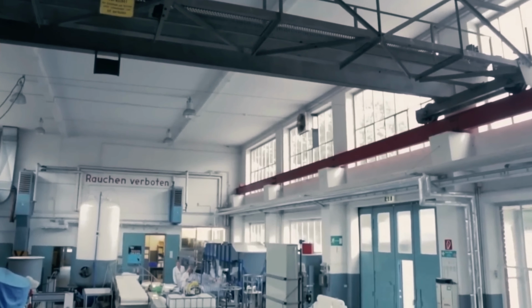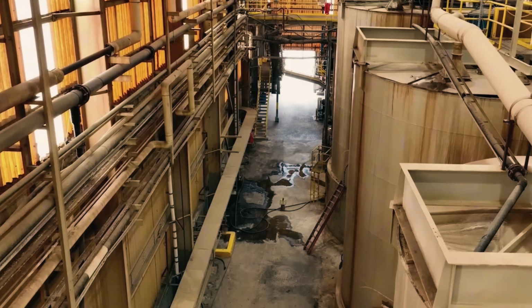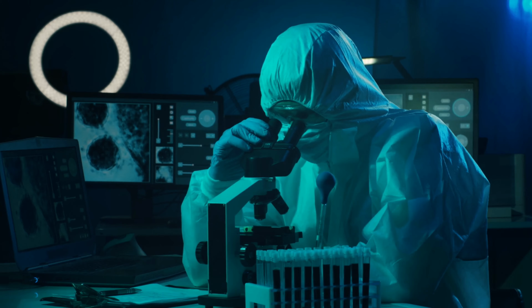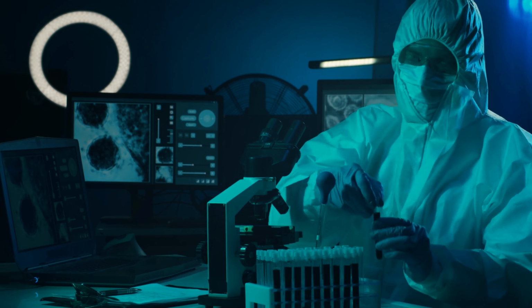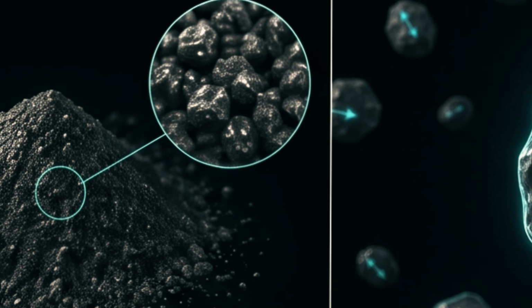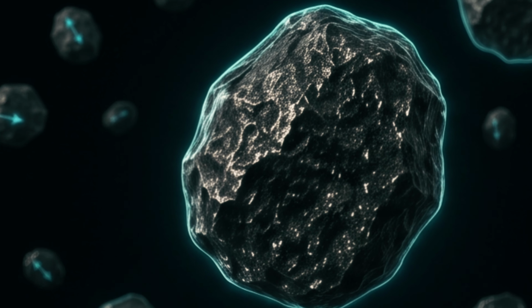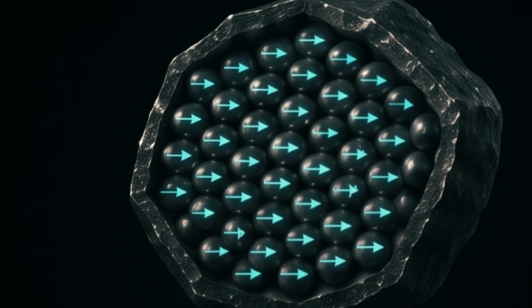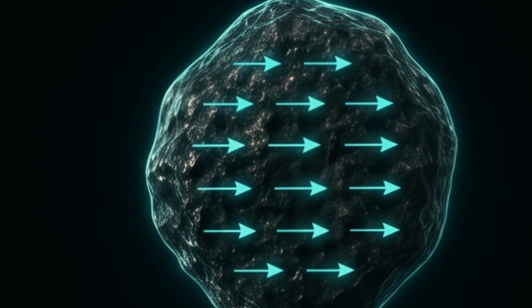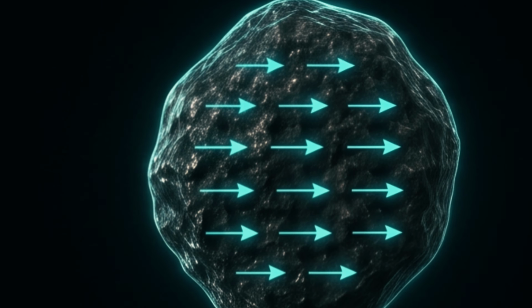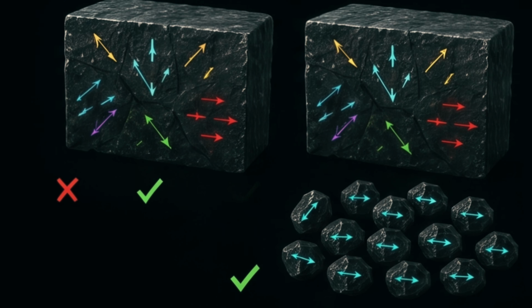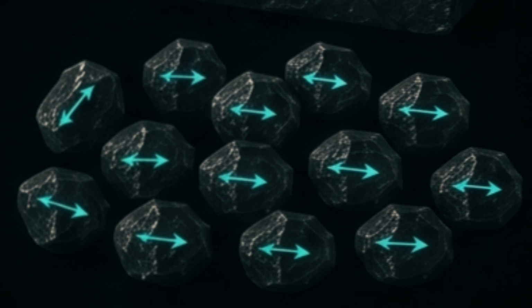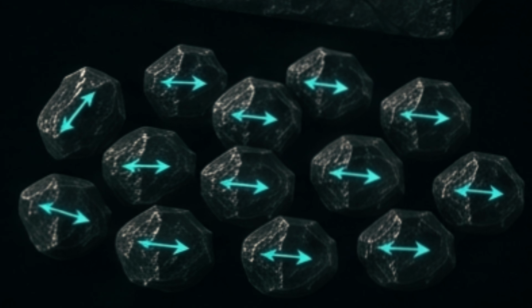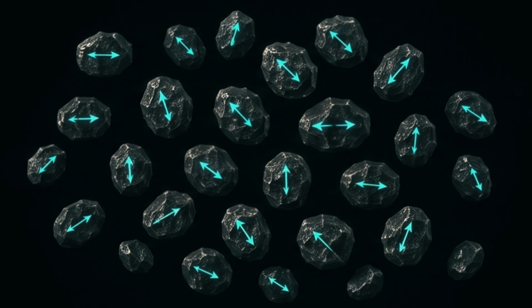That powder gets ground down even further, using specialized milling equipment, into particles smaller than a single grain of flour. Some of these particles measure just a few microns across, invisible to the naked eye. At this microscopic size, each particle is small enough to contain only a single magnetic domain, meaning every atom inside that one tiny particle is naturally inclined to point the same direction as its neighbors. This is the physical trick that makes the entire process possible. You can't force an entire solid block of atoms to align all at once, but you can force millions of these tiny single-domain particles to align one at a time in unison.